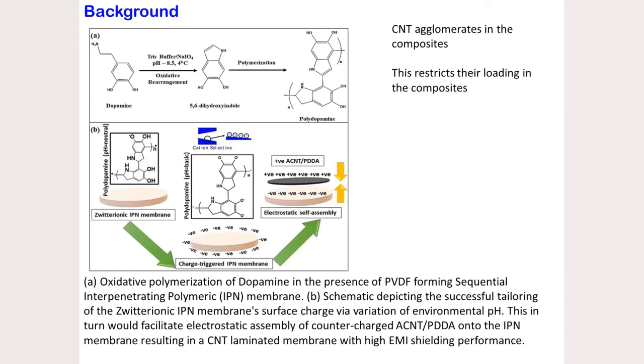So to this end, what our research group at IISc has done is we took an IPN membrane, an interpenetrated polymeric network. Why did we choose this membrane? Because you can trigger charge. And what we have done is we triggered charge and we added carbon nanotubes in such a way that there is an electrostatic assembly over the IPN membranes.